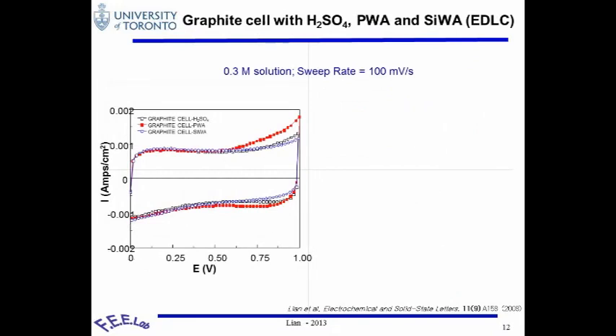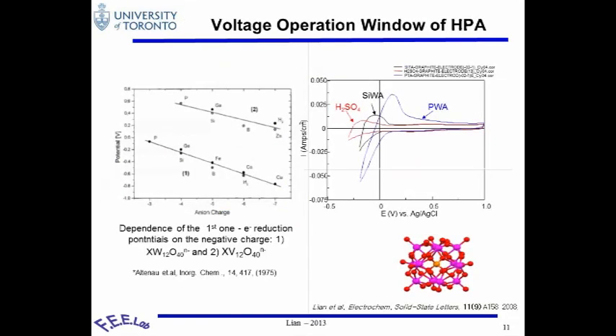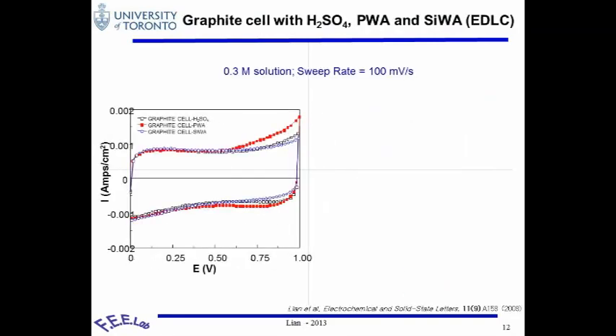These are results where, as we said, we're looking for a very rectangular shape voltammogram. These are three electrodes, one electrode in three different electrolytes. We started with sulfuric acid, the standard one, which is the black one, and then we looked at the phosphotungsten-based and the silicotungsten-based. What you can see is the red one here shows a little bit higher activity—if you go back to look at it, it's the tungsten-based one. We see there's a little peak here, so that's why there was a peak in the tungsten case.